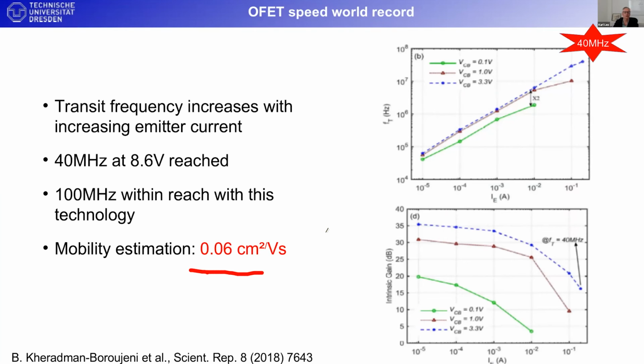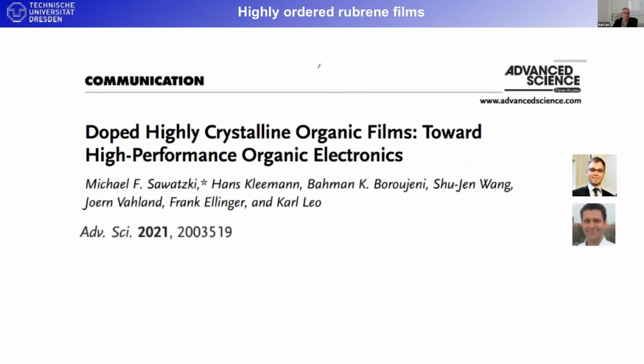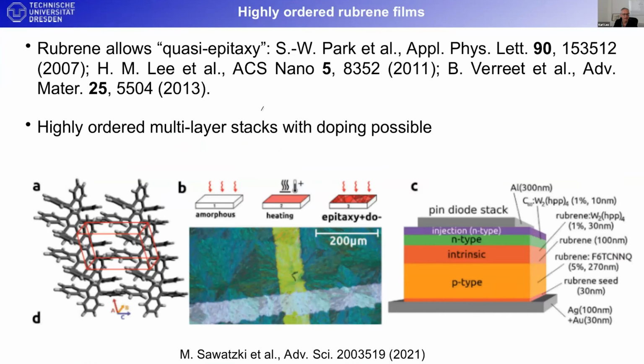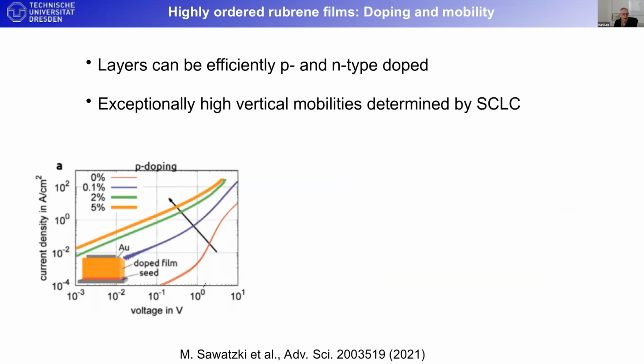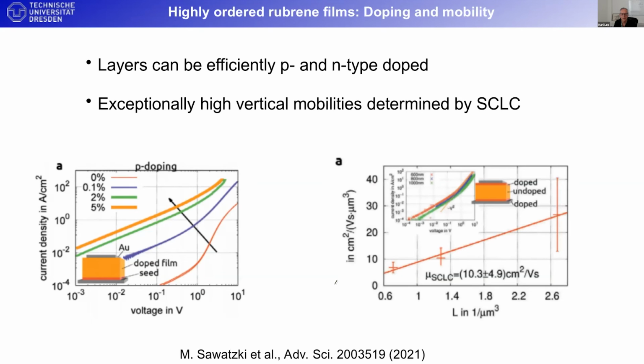But the key point is not to stay in the megahertz range. The key point is to reach much higher values, and recently we've made major steps towards that in work mainly driven by Michael Sawatzki and Hans Kleemann. And the idea is here to still use a thin film device, but with highly crystalline organic films, and therefore achieve much better properties. We are using an idea developed by some Korean researchers that rubrene, a specific organic material, grows epitaxial, quasi-epitaxial, by doing some annealing on a thin film and then growing epitaxially. And what we could prove is that you can grow complex device stacks, including doped layers, using this technology. And the doping increases conductivities by orders of magnitude, and still we achieve quite high vertical mobilities of about 10.